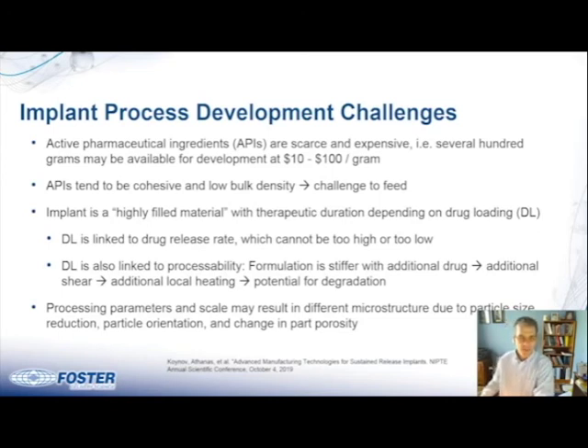So it has to be balanced not only for processability, in terms of whether you can actually form the implant, but even at higher drug loads, you will have more localized shear, and that's a potential for degradation. So it's something that you have to look out for when you're developing the implant.